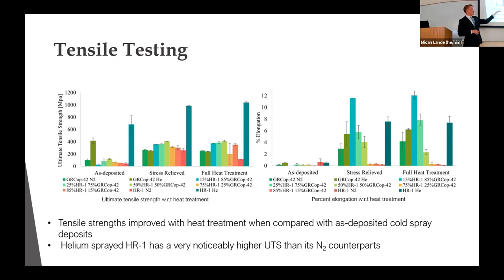These ultimate tensile strengths actually fall in line pretty closely to the pure extruded material tensile test done. So they're right in line with what we would expect, and they are higher than using other similar methods like direct energy deposit or other thermal methods instead of cold spray. The only problem with that, though, is although we do have higher tensile strength, that comes at the trade-off of having lower elongation, where we can see in the as-deposited case, there's almost no elongation whatsoever. These solids are so brittle. I mean, I broke several of them just trying to write on them with a Sharpie to label them. So there's no elongation whatsoever.